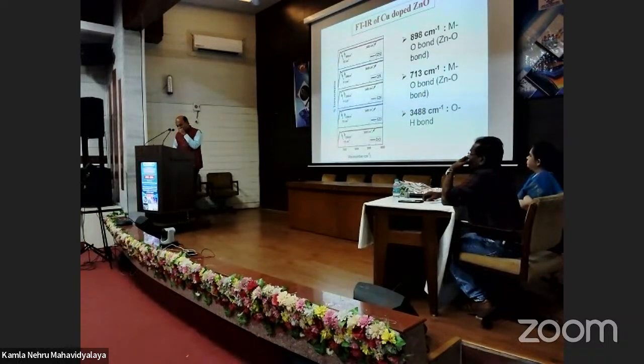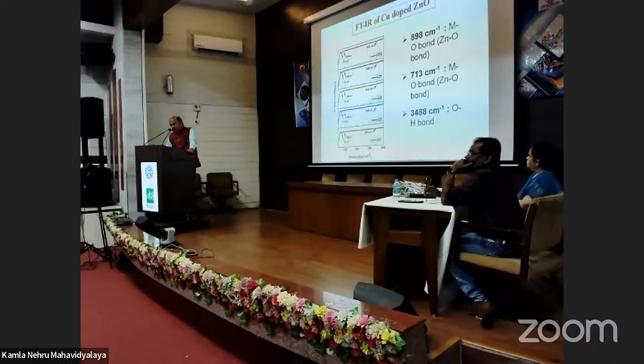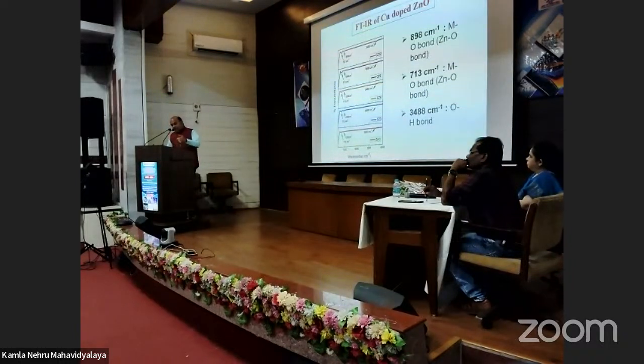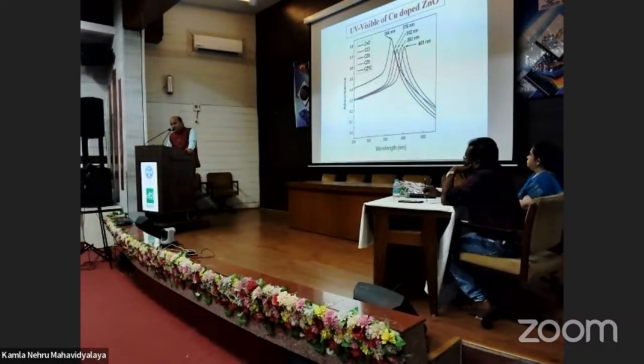FTIR of copper doped zinc oxide: the zinc-oxygen bond appears at 898 centimeter inverse, whereas another bond may be due to impurity, and there is a hydroxyl group at 3488 centimeter inverse. This is the UV visible spectra. If you look into this, the absorbance is changing from 364 to 401 nanometers.